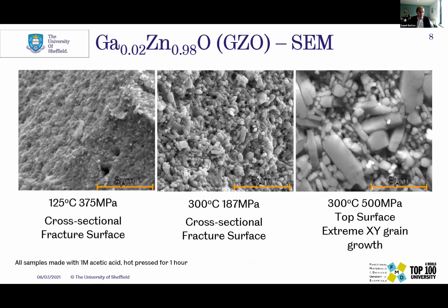So other work I did, to create the transparent conducting oxides that I mentioned, you need to increase the conductivity if you want to get anything close to indium tin oxide. Usually this is done with the introduction of gallium or aluminium, sometimes both. We did 2% gallium, some powder was produced for us, and we wanted to see if we could cold sinter it. The answer is yes.